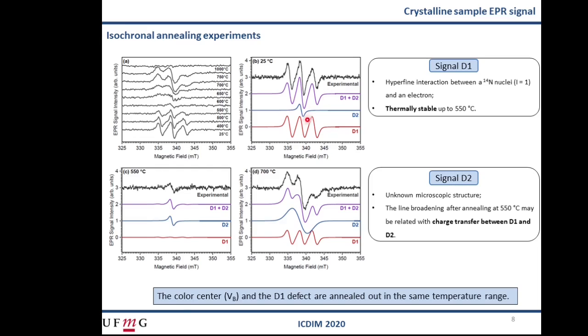At room temperature, for example, the signal D2 is very weak and its line width is comparable to that of signal D1. After that, the signal D2 is much broader and more intense, and the signal D1 reappears. So, the reappearance of the nitrogen hyperfine interaction accompanied by the broadening of signal D2 may be an indicative that both defects are transferring charge to each other, whereas the disappearance of the signal D1 along with the color center may indicate that the boron vacancy transfers charge to the defect D1 and both lose their paramagnetic state.